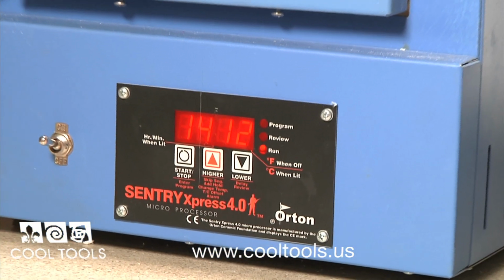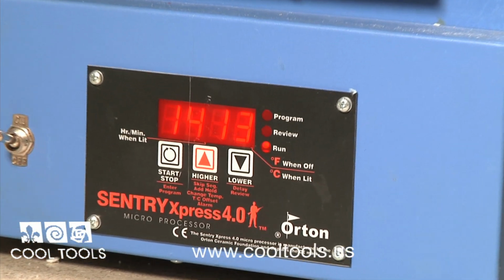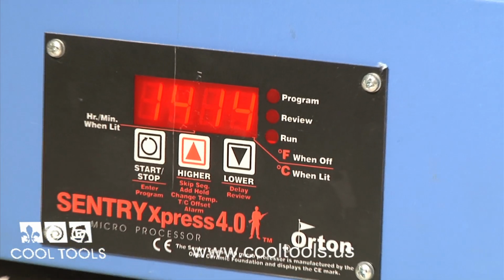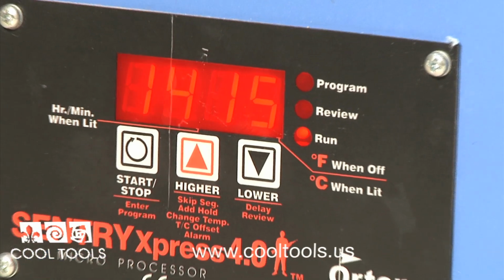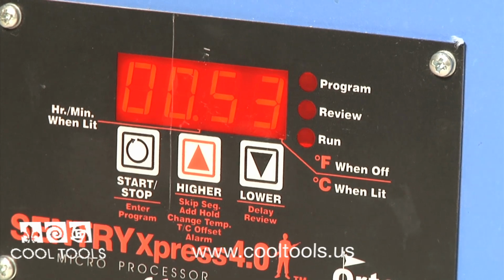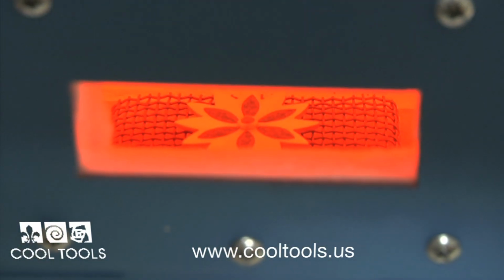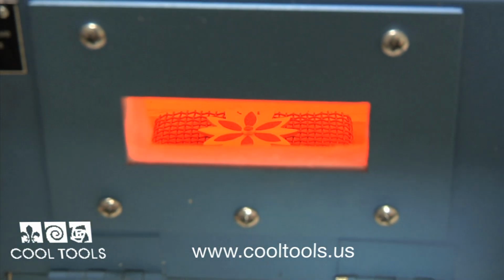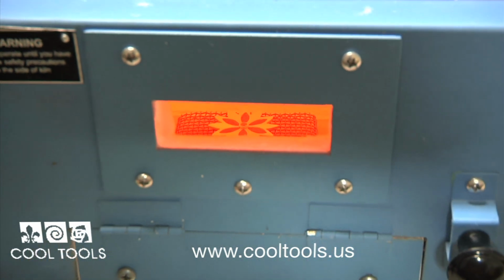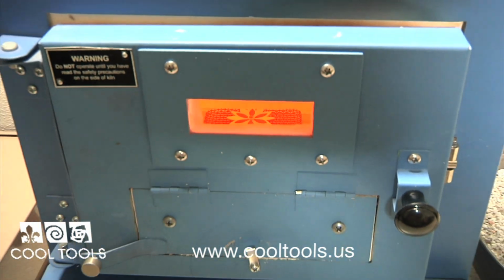Enamels fuse between 1400 and 1500 degrees. Your kiln will need to be hot when adding your enamels, so I set my Paragon SC2 to 1450. As long as your temperature stays above 1400 degrees after inserting your piece, your enamels will still fuse properly.